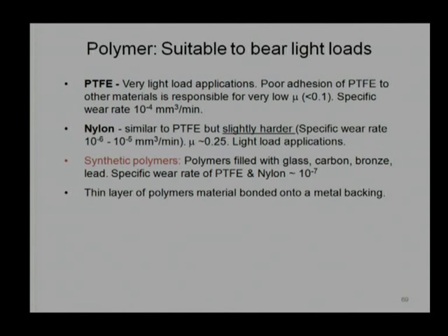Also, it is easily available in the open market. However, the only disadvantage of nylon in place of PTFE is a high coefficient of friction. The coefficient of friction is 0.25. That means we lose almost 2.5 times more energy compared to PTFE. Again, they are suitable only for light load applications. Their specific wear rate is lower by 10 to 100 times compared to PTFE. However, PTFE has a major advantage of the coefficient of friction, and we do not want to lose it. That is why many times we use synthetic polymers.